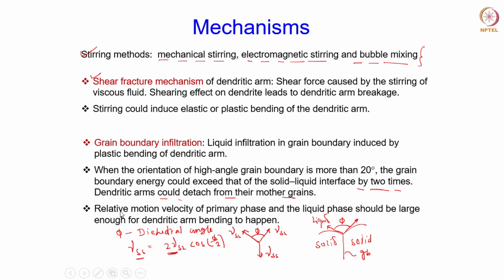But for this plastic bending to occur, we have seen that the relative motion velocity of the primary phase and the liquid phase should be large, and that is why the melt has to be agitated vigorously by one of these means.